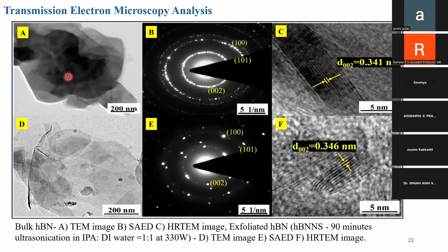Take a look at these transmission electron microscopy images. You can see that bulk HBN is so opaque that you cannot even see the layers. Here you can see that the layers are very visible, and it has been brought down to a minimal thickness. And this is the selected area electron diffraction, which will give you an idea of the single crystallinity or multiple crystallinity of the material. And definitely comes the HRTEM. HRTEM of the material is very important to find the d-spacing of the material.